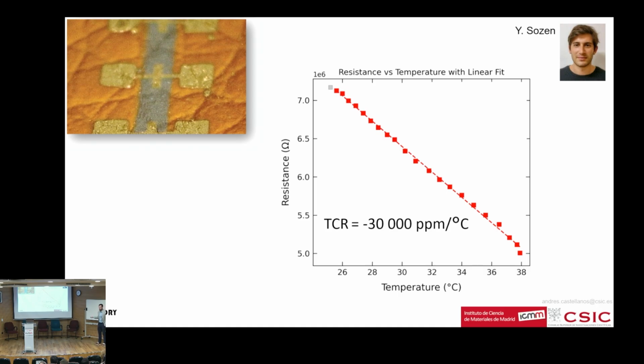If you go from 25 to, in this case, 38 degrees, because it's the physiologically interesting limit, you see a huge coefficient, TCR, of 30,000 ppm per degree. And if you compare this with a commercial silicon thermistor, they are typically on the order of 100. So 30,000 ppm per degree versus 100.